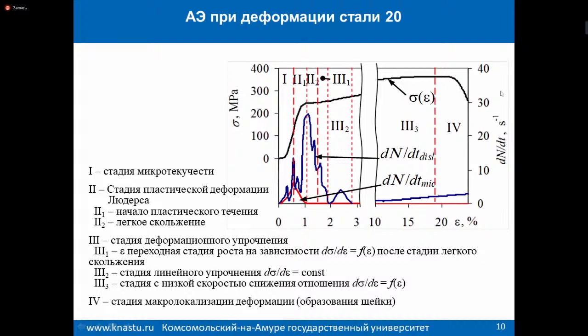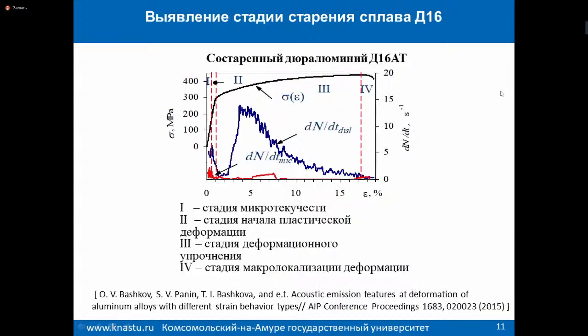And at the stage of elasticity or micro deformation, there can exist at the edges of the grains. So further was information about dislocation of cracks which go out of the surface of crystals. They may do it, but the level of registered signals is lower. Thus, further we have the active plastic deformation at the beginning, and it can be registered as a signal of acoustic emission.